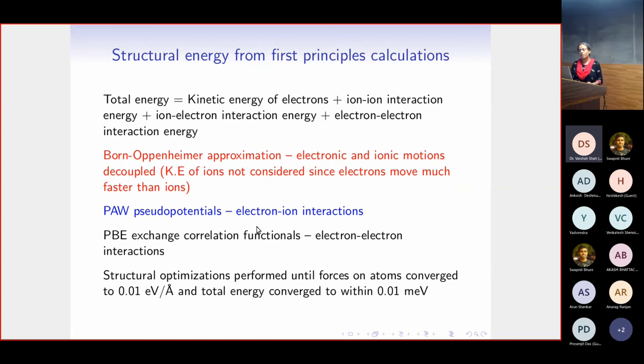And there are a few other approximations which are required to determine the accuracy of the total energy and everything that is related with the physical behavior of the system. One very important one is called the pseudo-potential approximation. It is very important because it reduces the complexity of the calculations and yet it gives us very good results. This approximation helps us to treat the electron-ion interactions. And for the electron-electron interactions, there are certain parameterizations that have to be performed to treat the exchange and correlation part of the electrons. There are different exchange correlation functionals, so sometimes we have to figure out which one is going to work well for our system. In this case, we have worked with what are called PAW pseudo-potentials, and we are going to use the PBE exchange correlation functionals.